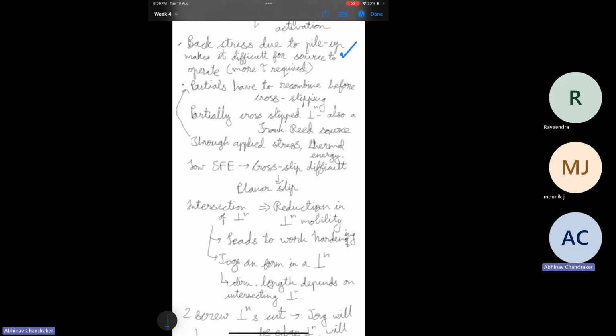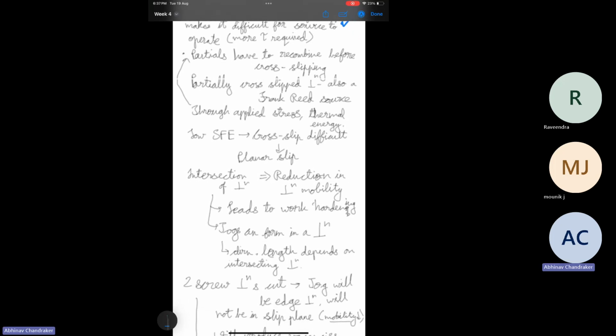Partials also, screw dislocation can cross slip, but partials have some edge character also. So that will restrict the cross slip phenomena. In order for a screw dislocation to cross slip, the partials which were formed due to dissociation of the screw dislocations will have to come together. Then it can cross slip, and then they can again dissociate to reduce the energy associated with the dislocation. This phenomenon of combination is called recombination.